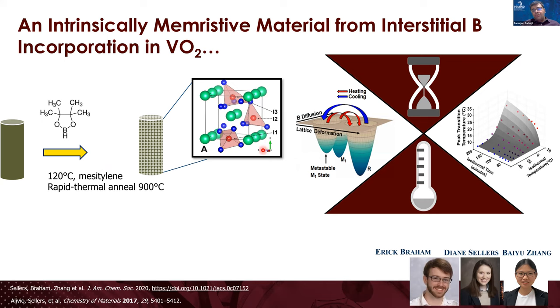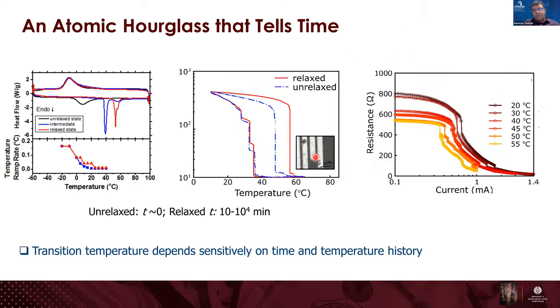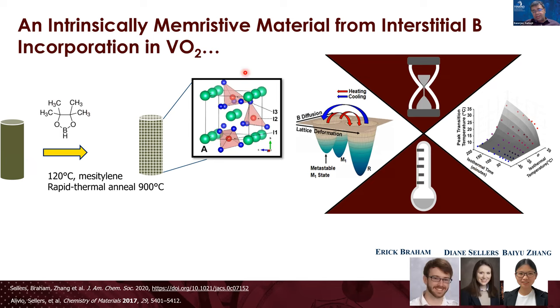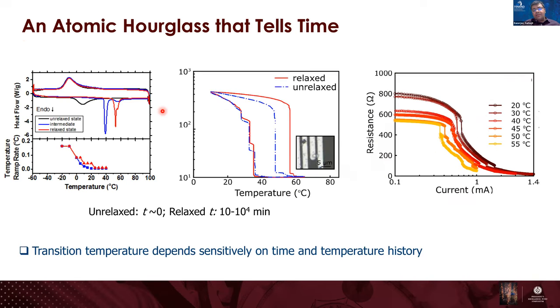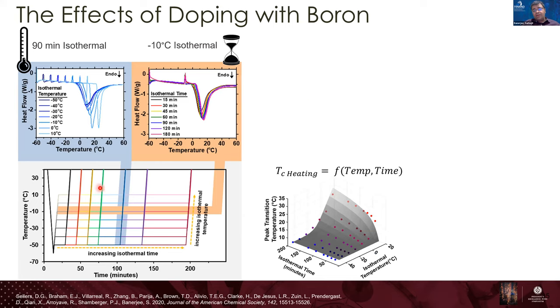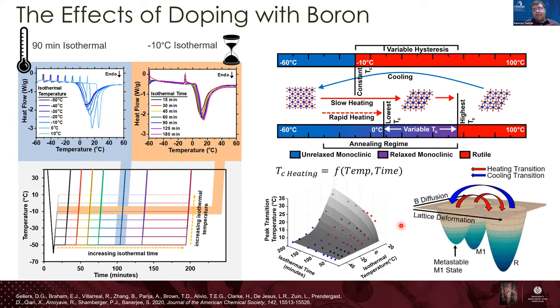So as you heat up boron doped VO2 and you cool it down, the boron is trapped in an unfavorable site and starts to diffuse. And as it diffuses, the structure relaxes. So as a function of time, the transformation temperature edges upwards, and it depends sensitively on how long it's been sitting at a certain temperature and what temperature that is. It's an extremely nonlinear behavior.